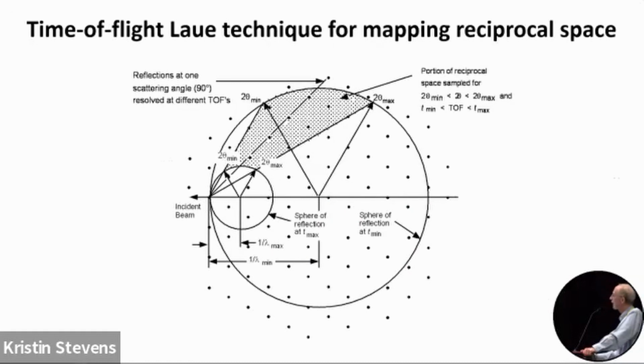So this shows the time of flight Laue technique in reciprocal space. Basically during each pulse, right at the beginning of the pulse, all the neutrons emerge, and then they sort themselves out by velocity. So the first neutrons to actually hit the sample have the shortest wavelength and the largest Ewald sphere. So that would be the large sphere here. And then towards the end of the pulse, the slower neutrons have the longer wavelengths, and they would have this Ewald sphere. And everything in between these 2 spheres can be sampled and measured.